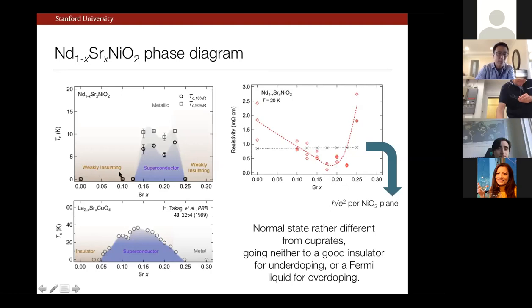In both cases, we have this rather weakly insulating upturn. Okay? And one way I can try to show you, or at least some of our thoughts on this, is to give you a low temperature normal state slice of the resistivity. Now, this is for all of the samples, or for several samples at each doping. So you can see the scatter, which is non-trivial. And yet the overall trend, I hope, is also very convincingly clear, shown by this dotted line.